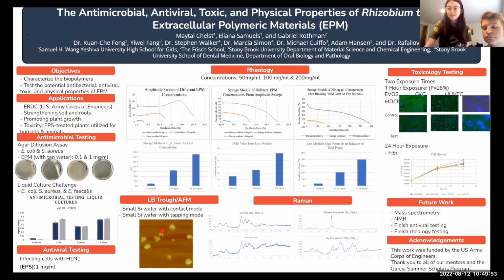Lastly, we did toxicology testing, and we did it with 2 separate exposure times. One was a 1-hour exposure on 3 different kinds of cells, MDCK2, gingival keratinocytes, and HUVEC. And the first thing you can see is the EVOS microscope, showing that they're both similar, regardless if they were treated with the EPM or not, and there was no statistically significant difference. Then we did a 24-hour exposure version on human dermal fibroblasts. And again, you can see that the EPM had no adverse impact on the cell count of the cells that we use.